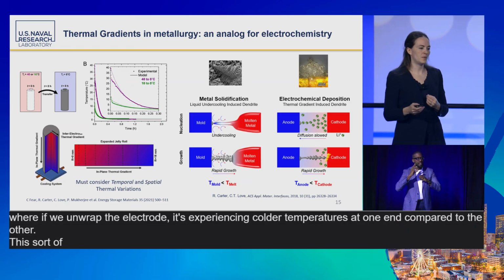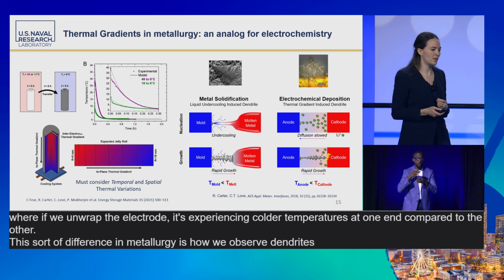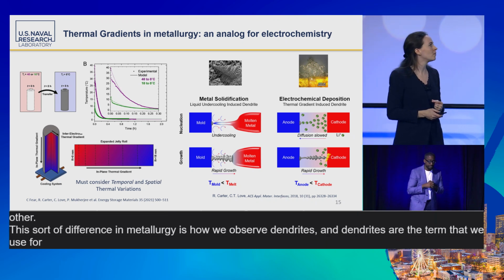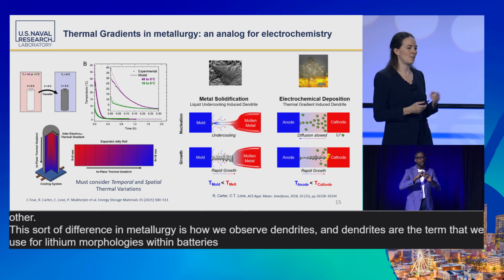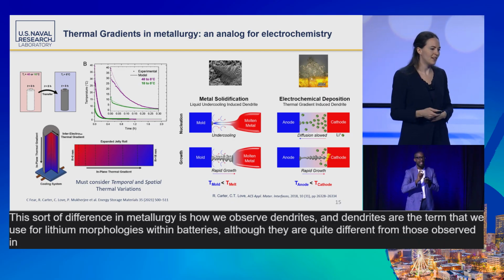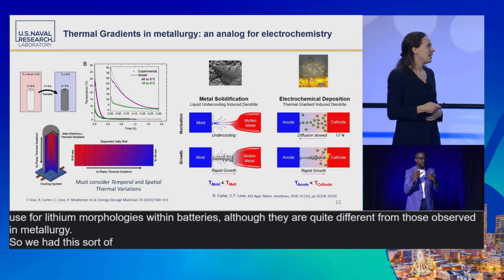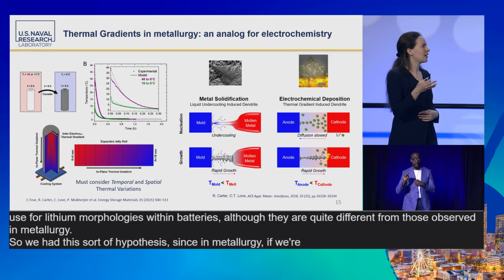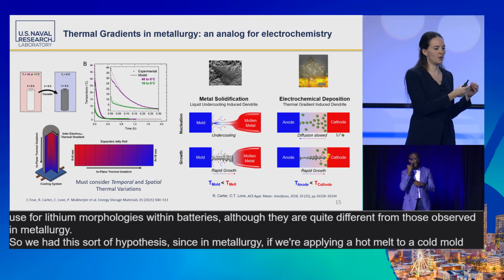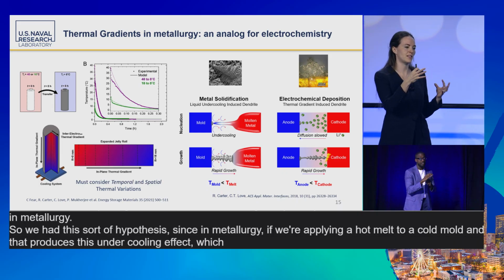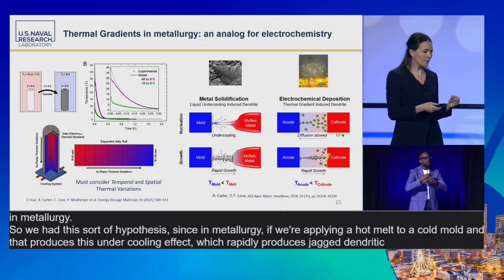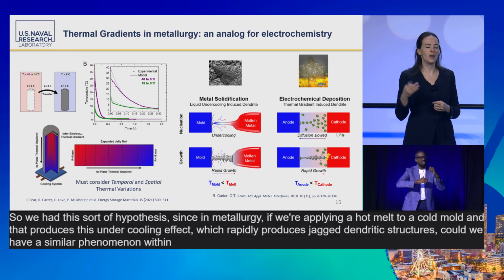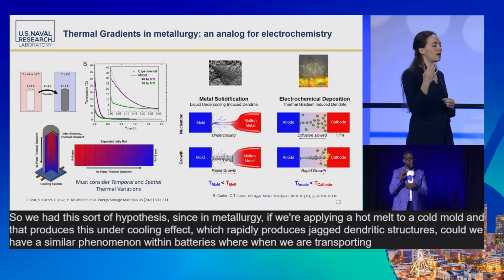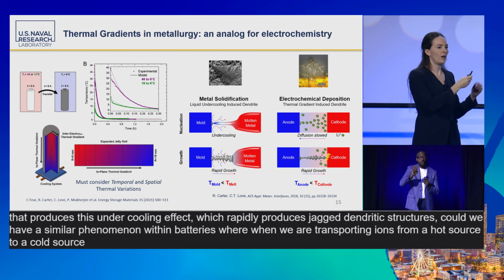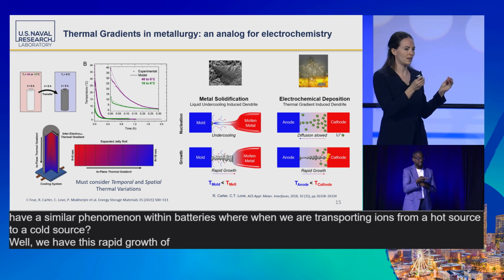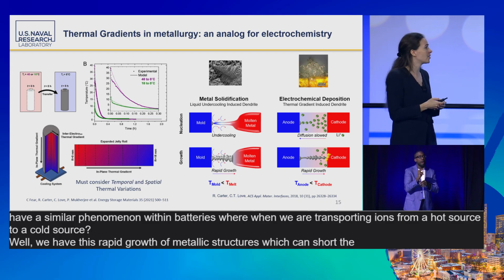This sort of difference in metallurgy is how we observe dendrites. And dendrites are the term that we use for lithium morphologies within batteries, although they are quite different from those observed in metallurgy. So we had this hypothesis. In metallurgy, if we're applying a hot melt to a cold mold, that produces this undercooling effect, which rapidly produces jagged dendritic structures. Could we have a similar phenomenon within batteries, where when we are transporting ions from a hot source to a cold source, we have this rapid growth of metallic structures which can short the battery internally?